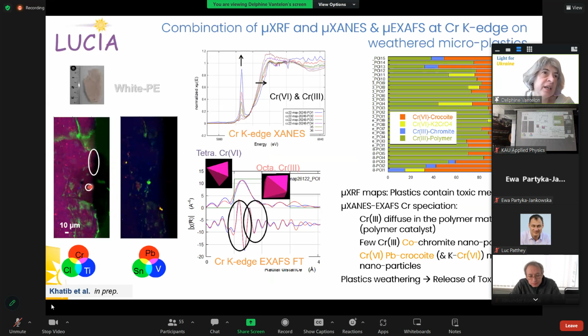And so clearly with the alteration, you see here at the hotspot of chromium, with the alteration, you have a release of these toxic metals into the environment. Performing XANES and EXAFS at the chromium edge in different locations of the map, users could observe that chromium occurs in this sample as chromium-3 linked to the polymer of the plastic, but also as a cobalt chromite nanoparticle, and also as chromium-6, which is the toxic form of chromium, associated with lead in crocoite, or with potassium as potassium chromate. So the plastic weathering, as said, released the toxic metals in the environment.